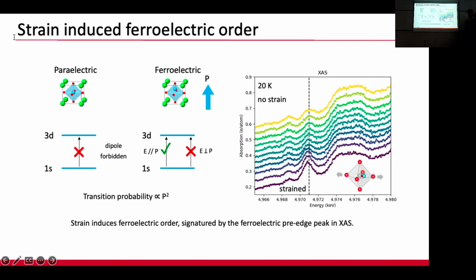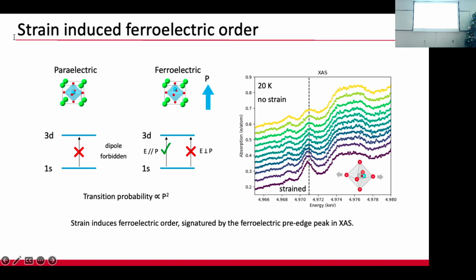Therefore, you see an enhancement of the peak, and the peak height, this transition probability, is proportional to this P squared. It's proportional to this ferroelectric order parameter squared. It's proportional to this order parameter squared.